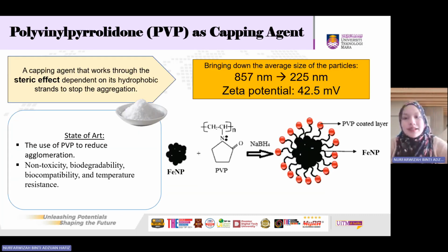There are a few studies that have been conducted to reduce the agglomeration of nanoparticles. One of them is by using polyvinylpyrrolidone, PVP, which brings down the average particle size from about 800 nanometers to about 200 nanometers with a zeta potential of about 40 millivolts. PVP is a capping agent that works through the steric effect dependent on its hydrophobic strands to stop the aggregation.